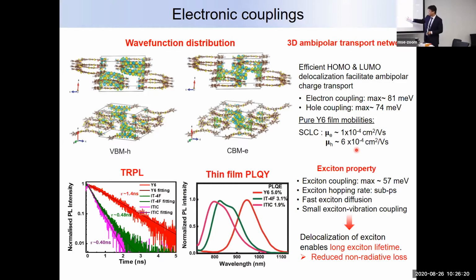Okay, and if we have a very fast hopping rate in the sub-picosecond, we can reduce the exciton and vibronic coupling with the molecule. Okay, so this is important, because if the exciton is decoupled from the vibration, we will have a more emissive exciton. So this is one of the reasons why the non-radiative loss in this particular material is so good, because they are very emissive materials.